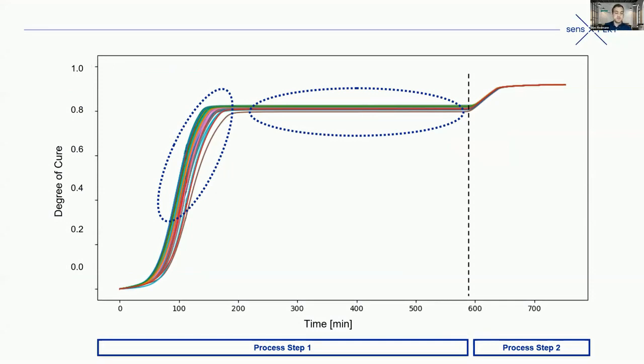There's these two steps of the process. And in this process step one, you can see there's a lot of deviation between the parts in that first 200 minutes. And because there's all that deviation between parts, just because of the size of the part, the mixing ratios, ambient conditions, maybe the temperatures are changing, there's just inherent variation in the process. And so because of that, they needed to have a really long hold time. So that's that second circle from 250 minutes to about 600 minutes. That's just a really long hold time to make sure everything stabilizes. So that ideally we can adjust that.